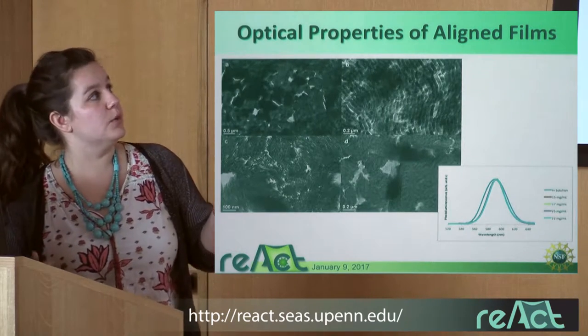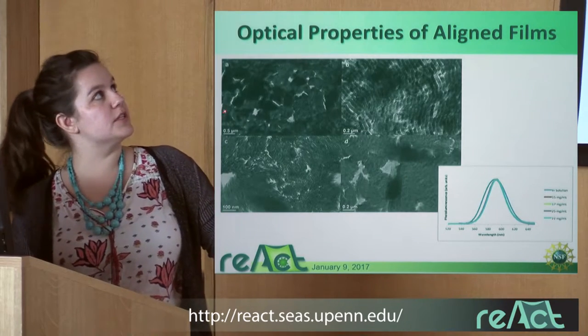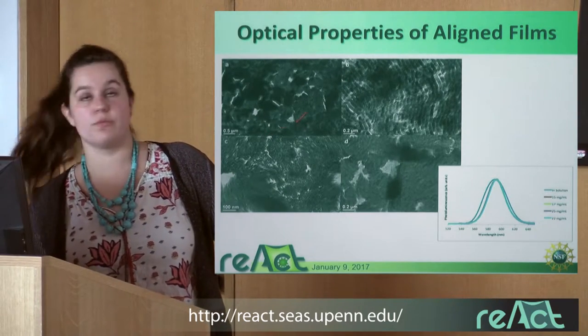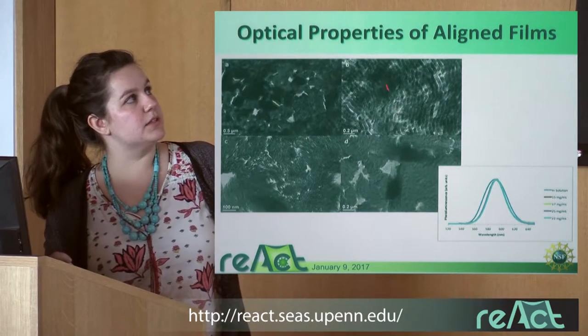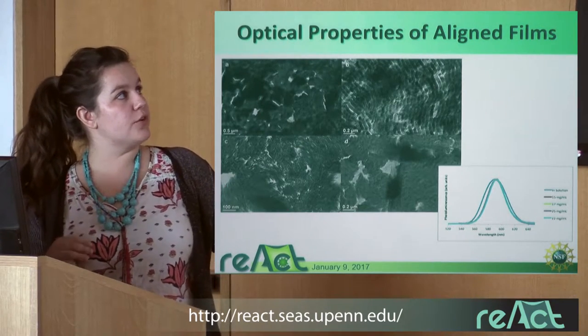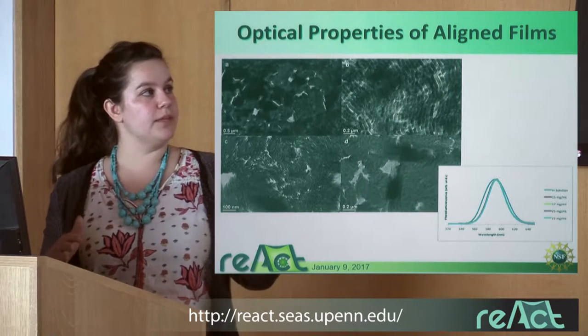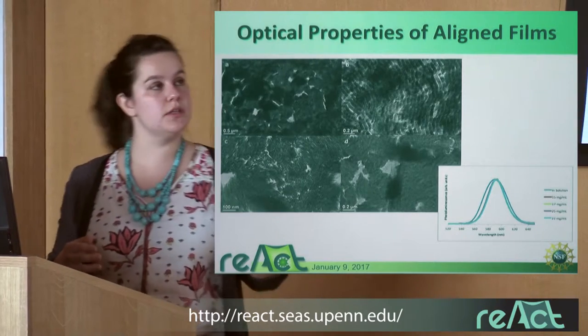Such as what I'm showing here, where these are self-assembled films of four different concentrations. This one was about 15 milligrams per milliliter, and it's turning out darker here than on the computer, but you can see there are some areas of horizontal alignment mixed with randomly dispersed rods. Slightly higher concentration gave us very nice bands of horizontally aligned rods. Then we got another film that was all vertically aligned, and another film that had some vertical alignment, but mostly randomly aligned rods.